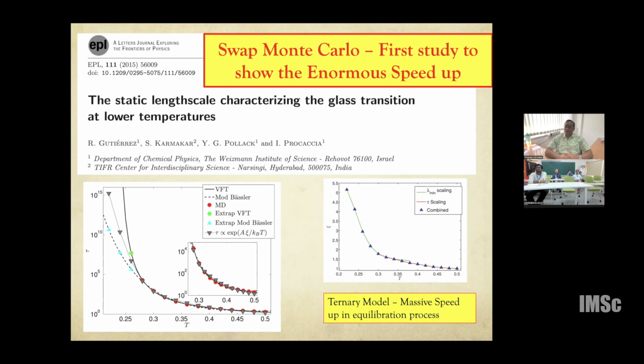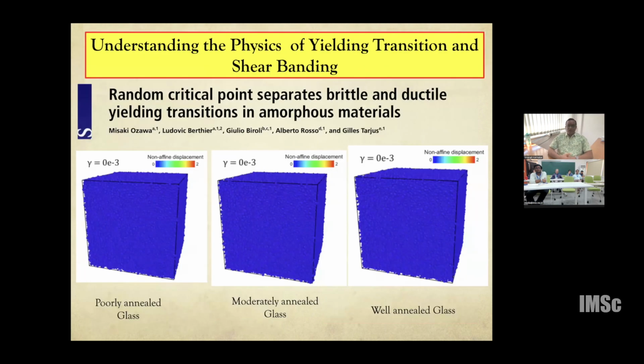length, and found for the first time that a static correlation length in this system can grow by at least a factor of 5 or 6, which was impossible to achieve before, and all previous literature data showed static correlation length growing by a factor of 2. So this was a significant advancement in terms of how you can access low energy glassy states, which was later picked up, particularly by the group of Ludovic Berthier and his collaborators.